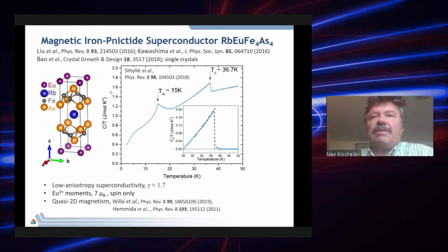And again, a magnetic family of this form was discovered. It was rubidium, europium, iron 4, arsenic 4, or instead of rubidium, cesium can also be used. So this material has very high, maybe the highest in this family, close to 37 Kelvin, followed by a magnetic transition at 15 Kelvin, and it's lower than in the parent material, mostly because the distance between europium is twice as compared to the parent material. It is characterized by low anisotropy, the anisotropy factor is only 1.7, and quasi-two-dimensional magnetism, and the magnetic transition is close to the BKT transition. This explains this interesting kink-like shape of the specific heat transition.